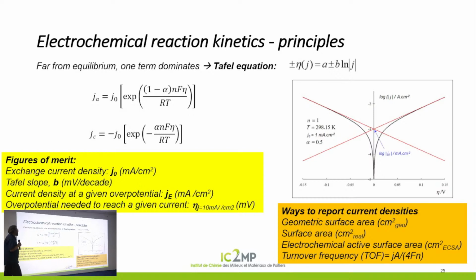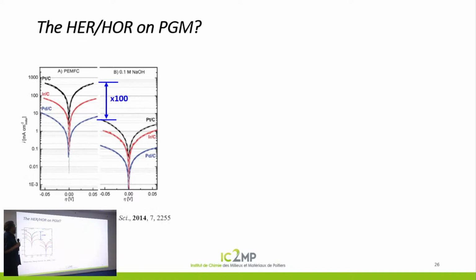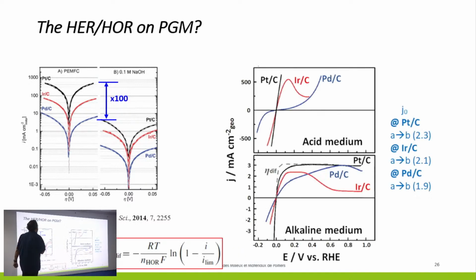All right. So now here are the experiments. Look here. We have platinum, iridium, and palladium for the hydrogen oxidation and reduction reaction. When you change from the acid to the alkaline, there is almost 2 orders of magnitude less activity than in the acid. Why so? I'm not asking for an answer, all right? You will see the answer later.